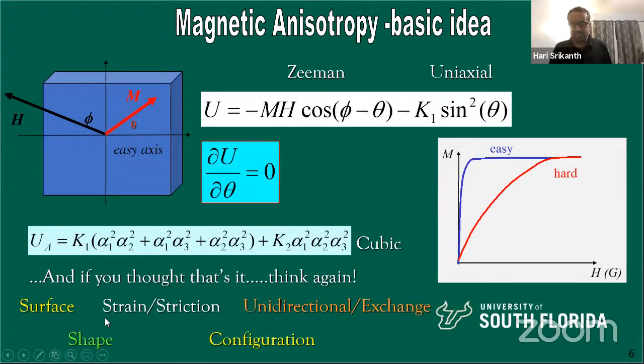Shape is easy to understand. You can make nano rods, and there's a preferred orientation. For example, the longitudinal direction, where you can easily magnetize it. So there's a distinct shape anisotropy there, which you can control. I'll show you how we can make these nano rods, and they're very important elements for this application. Strain is important because you can have, for example, thin films. You can have a substrate which is different from the magnetic film on top, and the strain at the interface can result in contributions to the anisotropy. This is the magnetoelastic contribution, and that can be used to tune the shape of the hysteresis loop.